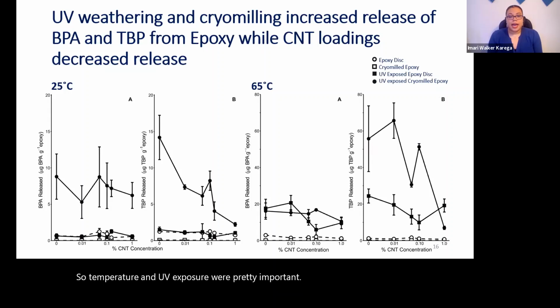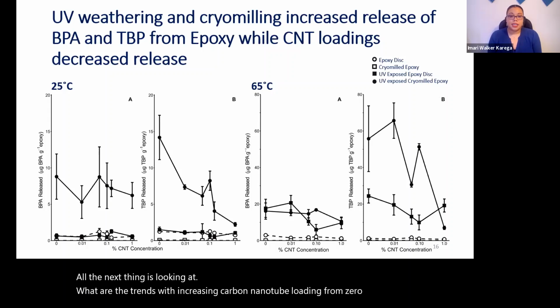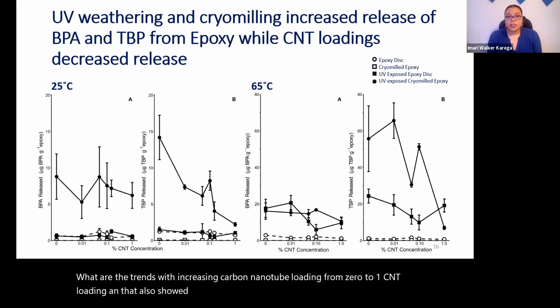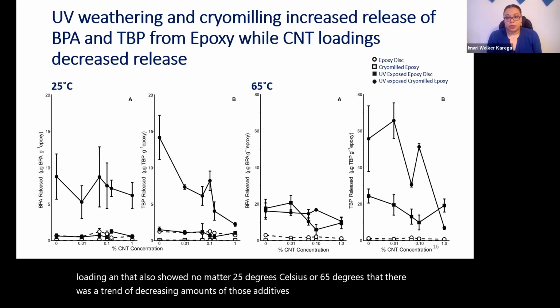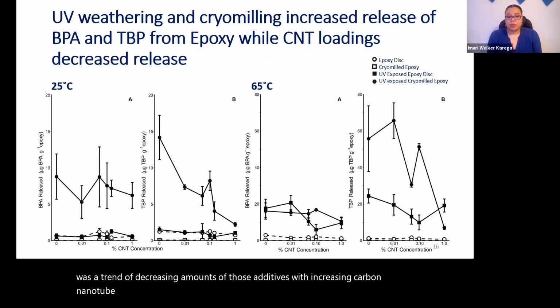The next thing is looking at the trends with increasing carbon nanotube loading from 0 to 1% CNT loading. That also showed, no matter 25 degrees Celsius or 65 degrees, a trend of decreasing amounts of those additives with increasing carbon nanotube loading, especially more relevant for the tert-butylphenol additive itself.